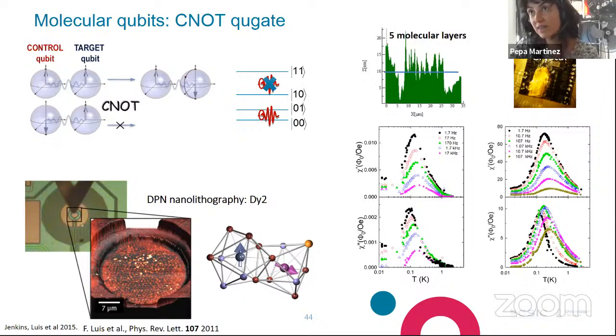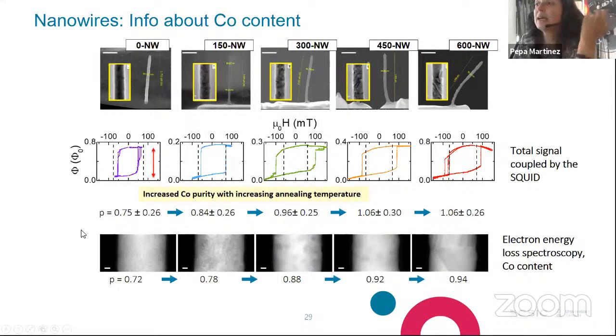Yeah, so you mean if we can quantify the... Yeah, but we need to use also numerical simulations. I mean, we do that actually. This is, for instance, what we did with the measurements performed on the nanowires, and the results were quite good, by the way. The only experimental information we have is the amount of magnetic flux. To translate that into magnetic units, we need to know precisely the shape of the particle and the position of the particle with respect to our nanoSQUID. Then we perform magnetic simulations, and we also simulate the superconducting currents flowing through the device, and we estimate how these flux units convert into magnetic units. But it's not fully experimental, as I told you. Yeah. Got it. And the results are, for instance, as you can see here, quite nice.